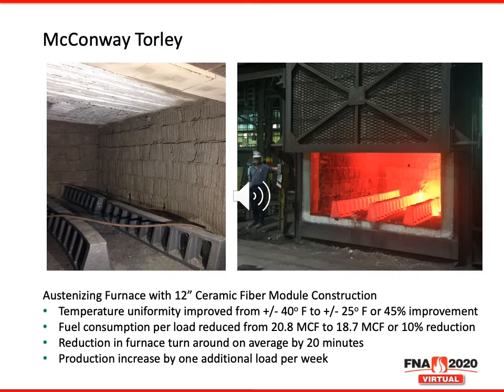Fuel consumption per load was reduced from 20.8 MCF down to 18.7 MCF, or a 10% reduction. Turnaround time reduced on average by 20 minutes. Due to the reduction in turnaround time, a production increase was realized by 1 additional load per week.